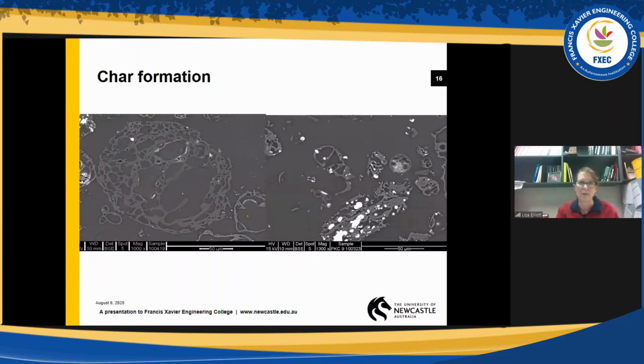So this is a coal for a power station. This has come from a vitrinite particle, and you can see it's a bit like a foam. It's a char that's been sectioned across and looked at under an SEM. And it's got large pores, small walls. This one on the right has come from an inertinite particle, and really it has swollen, but it's only swollen a little bit. And you can see the pores that were in the particle initially have only just expanded. So char formation really does depend on which particle it comes from.